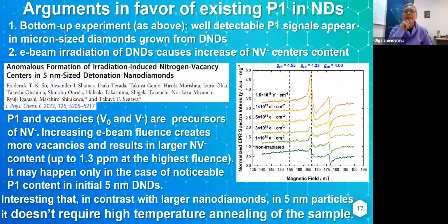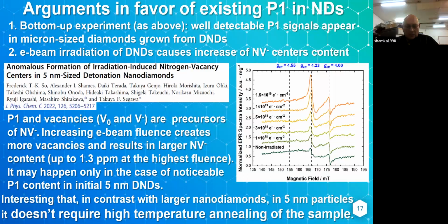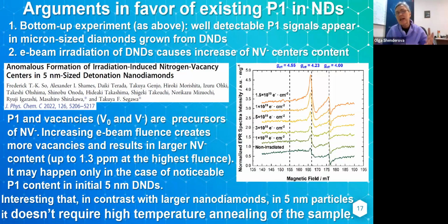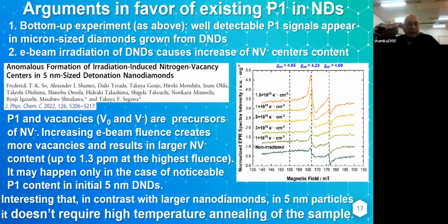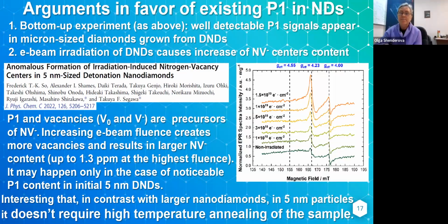Another question: maybe let's take a good particle by your criteria, for example 70 or 80 or 90 nanometers in size, HPHT. And if we would surround it with some magnetic noise species, molecular species, say of non-diamond origin, can you observe broadening of hyperfine structure due to multiple artificially induced species, I don't know, some nitroxides or maybe metal like gadolinium? No, broadening definitely we can. In P1, right? We can observe it.